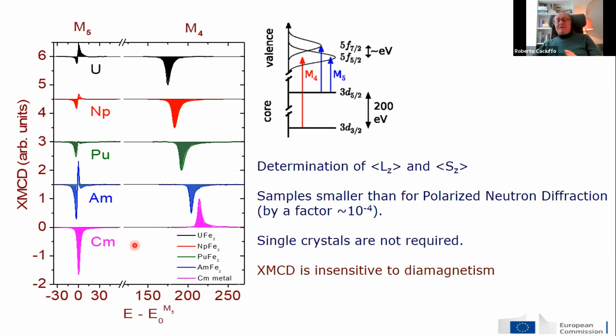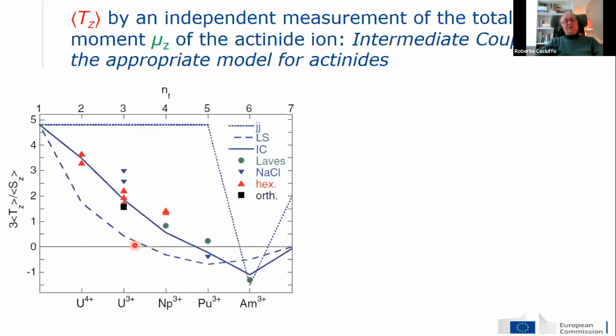The advantage of the technique in determining orbital and spin moment compared to polarized neutron diffraction is essentially in the size of the sample needed, which is up to a factor 10,000 smaller for XMCD than for polarized neutron diffraction. Also, you don't need single crystals to carry out these measurements. And if you are studying a superconducting compound, you can take advantage of the fact that XMCD is not sensitive to diamagnetism, but will explore only the behavior of the 5f of the interrogated shell.